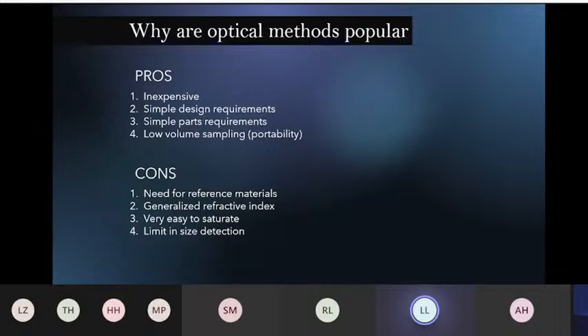The cons, of course, is that because scattering is very dependent on the absorptivity of the particles, there is a need for reference materials, unlike any of the other techniques. So in most cases, what happens is that there's a generalized refractive index that's used in the equations in Mie scattering to give an average characterization of the particles. So whether the particles are highly scattering or low scattering particles, they are summarized or averaged out into a generalized refractive index.